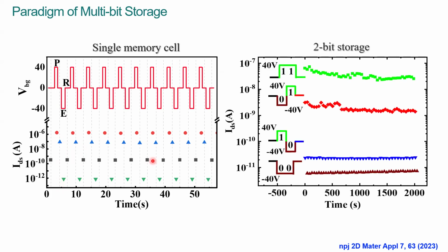Similarly, if you use a multiple number of pulses, like 1 1 0 1 1 0 0 0, this is a 2-bit logic. And this is the retention measurement taken after giving this kind of pulses. You can see that we can achieve 4 different memory conductance states by playing with pulses.